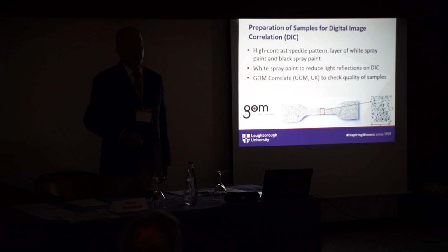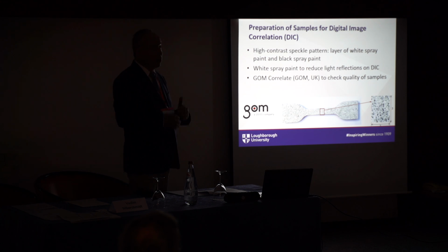Then there is an inevitable problem, if you have done this, which is the challenge of putting the speckled pattern on the surface. One reason is that the surface of the polymers is not always very suitable for this, and secondly, the level of deformation is relatively high, so in many cases when you apply relatively large deformation, you get the speckled pattern peeling off, which we will definitely try to avoid, because then we will get the wrong information.